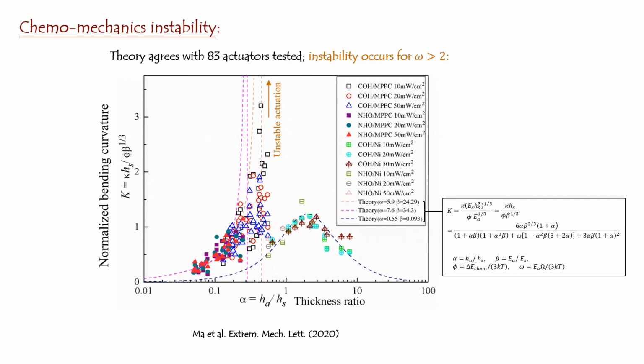Okay, so you have to choose the right system, the right material in the system, so that the normalized activation energy is larger than 2, and then the alpha is the value predicted by this equation. There is a singularity, mathematical singularity, when alpha is this magic number. So that's the theoretical guide. Experimentally, we were able to achieve just a few points. So altogether, there are something like 83, 84 actuators that the student has made, and only a few would encounter that instability.